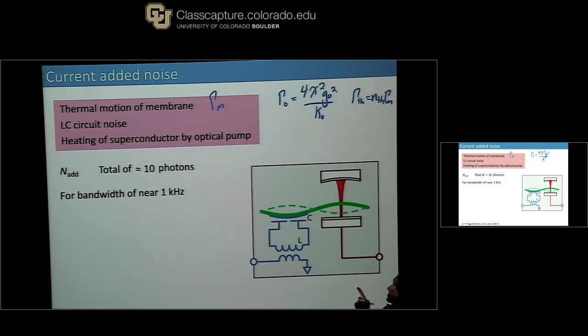Okay, and then the third one is what I think of as the thing we've ultimately been most scared about, and is perhaps the most fundamental limit in some ways. Not quite fundamental, but very important in the sense that we have to have light down by where the superconductor is. And if any of that light hits the superconductor, that can be a problem. And it's hard to quantify, too, because quantifying very small amounts of scattering and understanding where that light goes is actually a very difficult problem. Like in LIGO, like we were talking about yesterday, dealing with very small amounts of scattering and where that light goes is one of the things that they definitely worry about, and is a really hard problem.